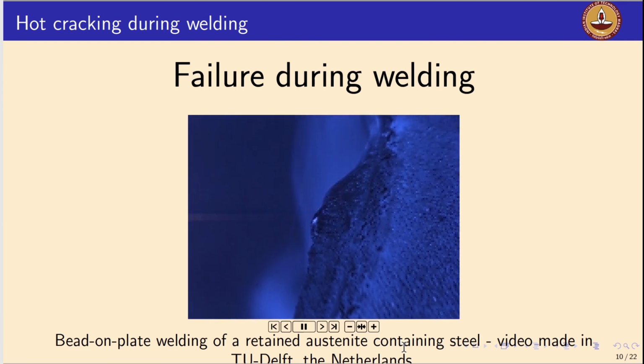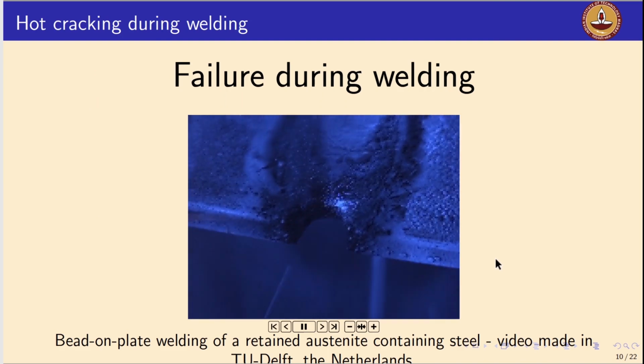Because if you look at the chemistries I showed you in earlier slides, this contains carbon of about 0.35 to 0.5. So if it is 0.4% carbon, the material is already highly susceptible to hot cracking. And apart from the carbon, we also have high manganese and chromium, for example, and some amount of phosphorus and sulfur as well from the fluxes we add. And those chemistries are notorious for hot cracking. So if you don't control the alloying elements in the weld, we end up just producing a cracked weld.